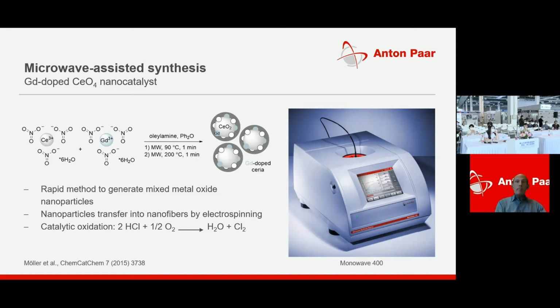In our application, the obtained nanoparticles have been harvested by first centrifugation and drying, and were characterized in terms of their hydrodynamic diameter, which was about 20 to 30 nanometers. In a subsequent process step, this nanocatalyst was embedded in polyethylene oxide nanofibers, which were obtained by electrospinning prior to its use for the oxidation of hydrogen chloride.